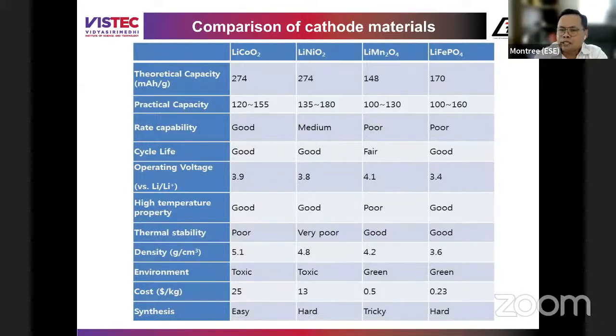But if we move to NMC, actually NMC started from LCO. LCO is the first cathode material, by Professor John B. Goodenough. And after that, he and his colleagues and communities modified or changed the element from cobalt to nickel, from cobalt to manganese, and so on. And we have different structures, right? The good thing about this is safety and long cycle life. The bad thing is the lower capacity and lower operating voltage, only 3.4. NMC is about 3.6, 3.7, LCO up to 3.9. The volt is different, right?